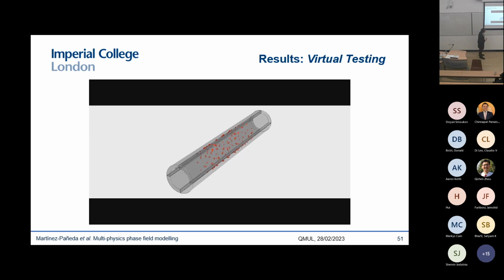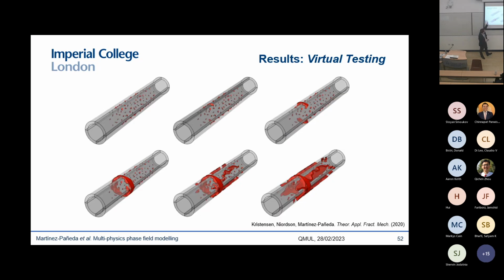Here we apply the in-service conditions. This is a riser pipeline, I think. You can see how the defects eventually start growing, they merge with neighboring defects, and eventually you get this complete failure of the pipe, which you can see here in a more extended version.